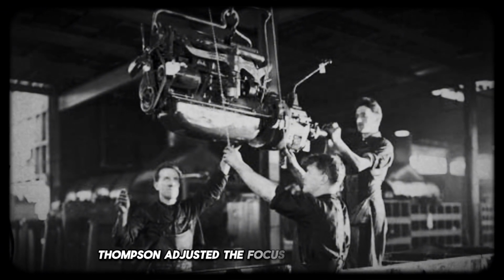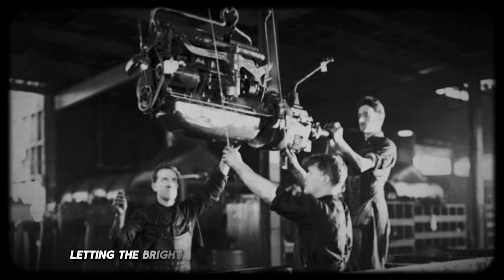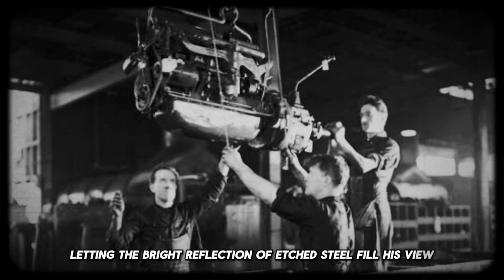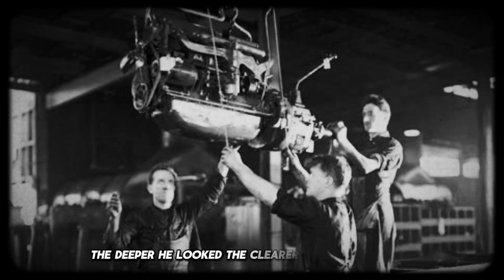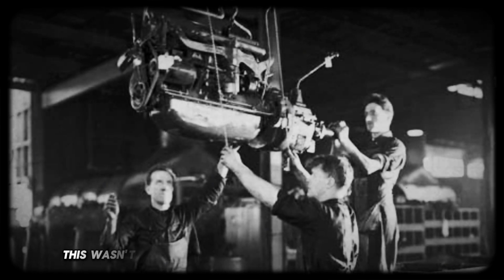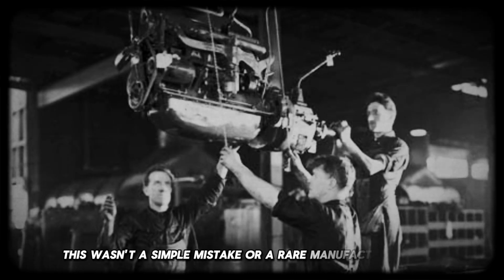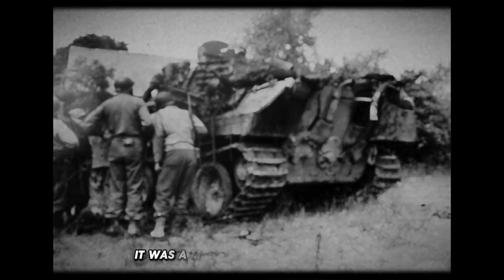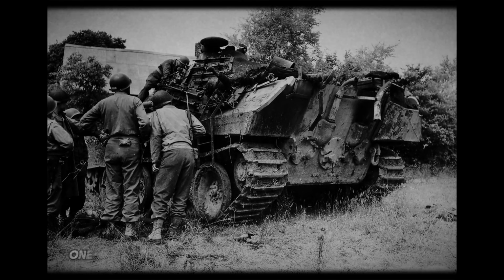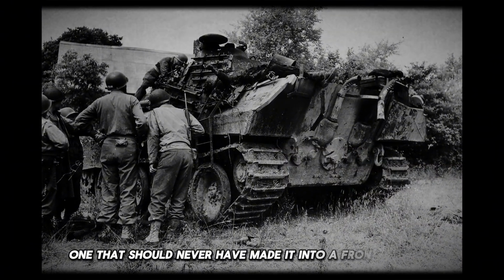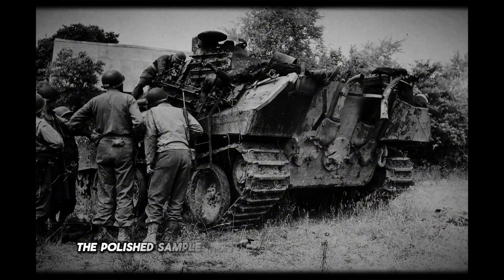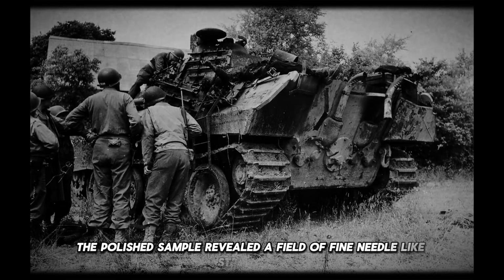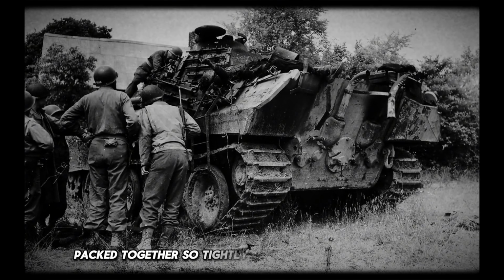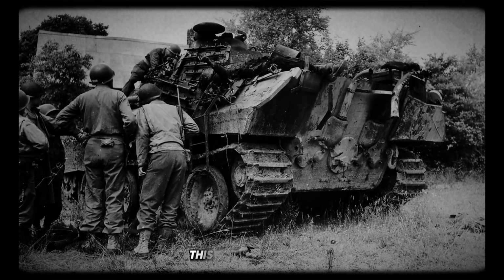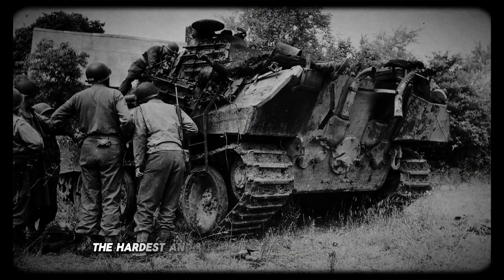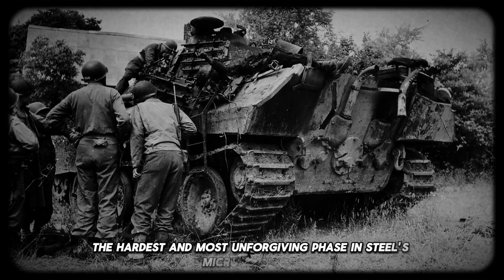Thompson adjusted the focus of the microscope, letting the bright reflection of etched steel fill his view. The deeper he looked, the clearer the story became. This wasn't a simple mistake or a rare manufacturing flaw. It was a metallurgical warning sign, one that should never have made it into a frontline tank. The polished sample revealed a field of fine, needle-like structures packed together so tightly that they almost shimmered. This was martensite, the hardest and most unforgiving phase in steel's microstructure.